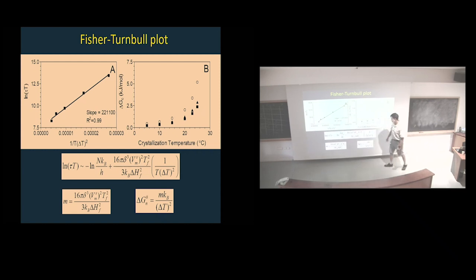That long one that looks like a nightmare? And the plot you have to do, if you rearrange it, is your induction time times the temperature that you set it at. And on the other side, you have the temperature and the delta T that you use. All you need is temperatures. And so if you do that plot, notice here, natural log of tau T versus 1 over T delta T squared, you get a straight line, if you're lucky.